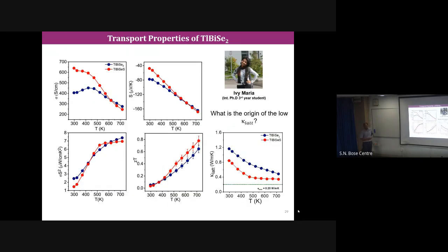So then we have measured the thermoelectric transport property. Don't worry about the solid solution compound. This compound shows moderate electrical conductivity, good Seebeck coefficient value, and very low thermal conductivity, and this is a negative Seebeck coefficient. So N-type materials are very rare in thermoelectrics. This is one of the best N-type materials in thallium bismuth selenide, one of the highest in the world.